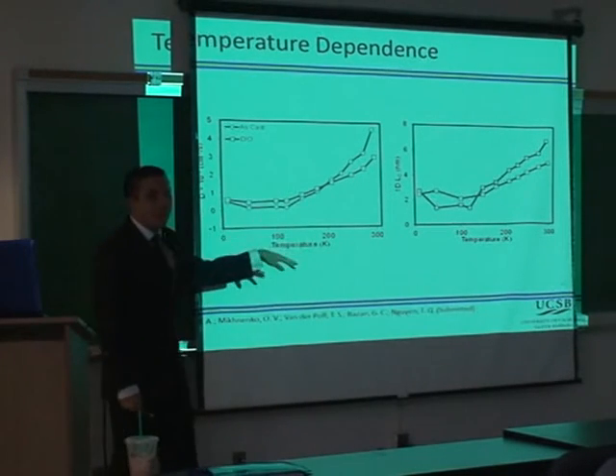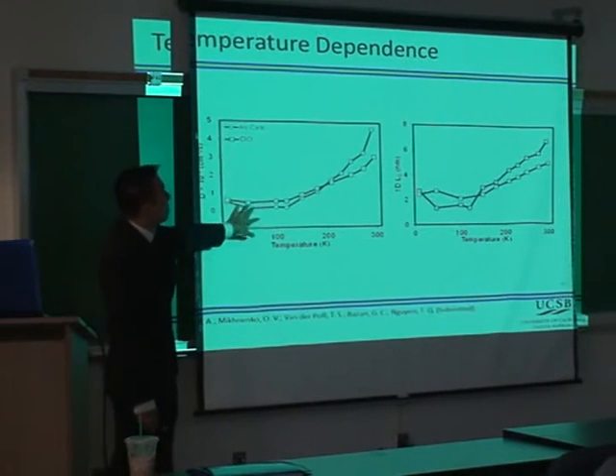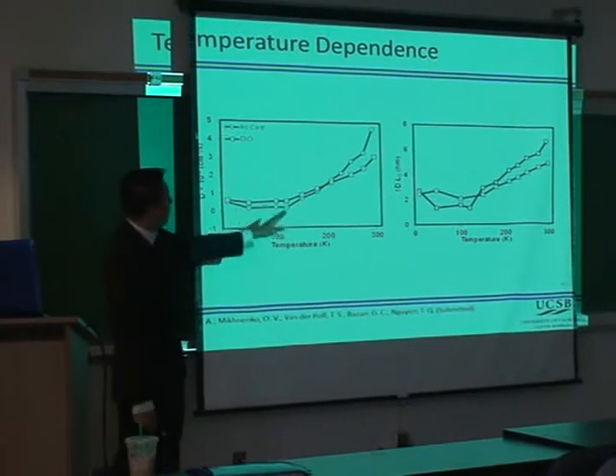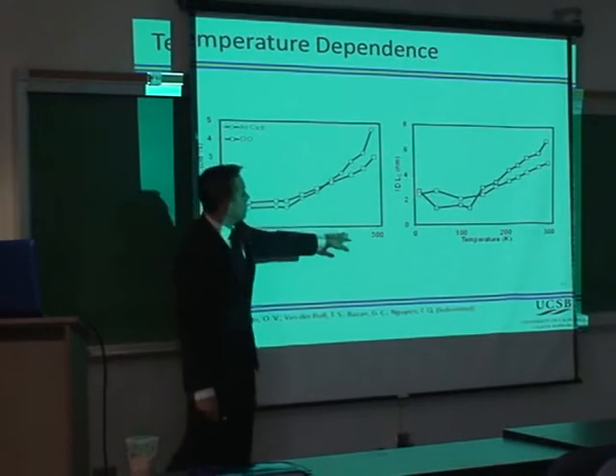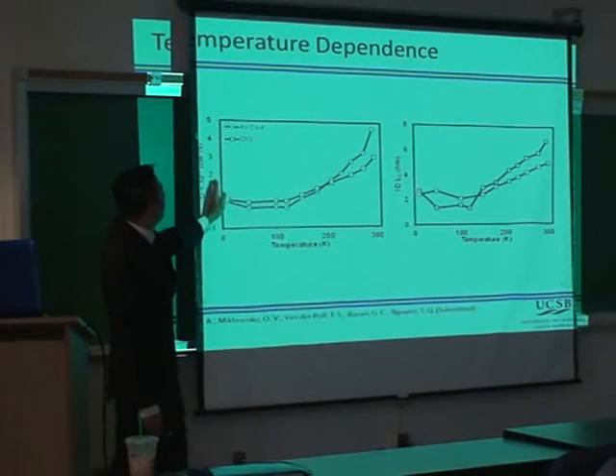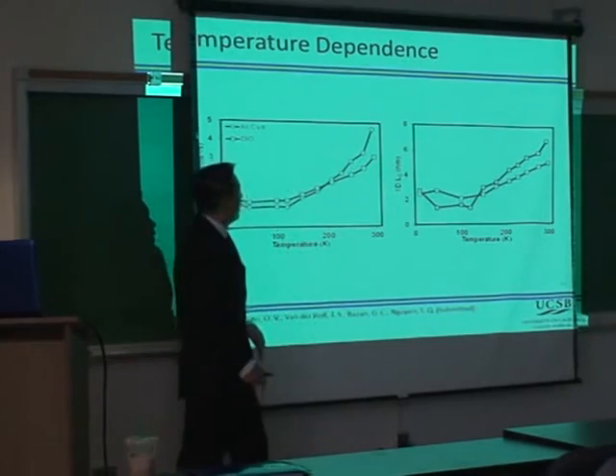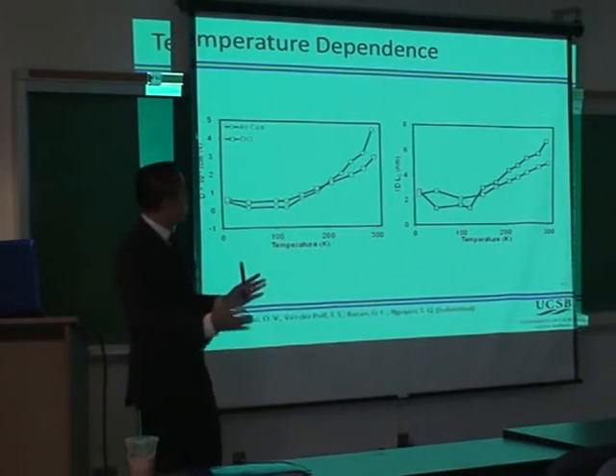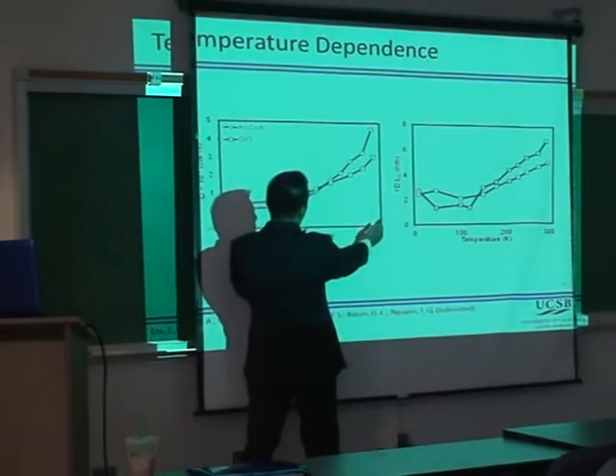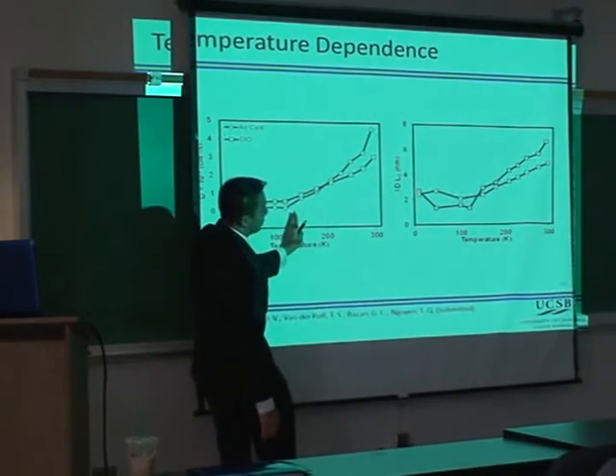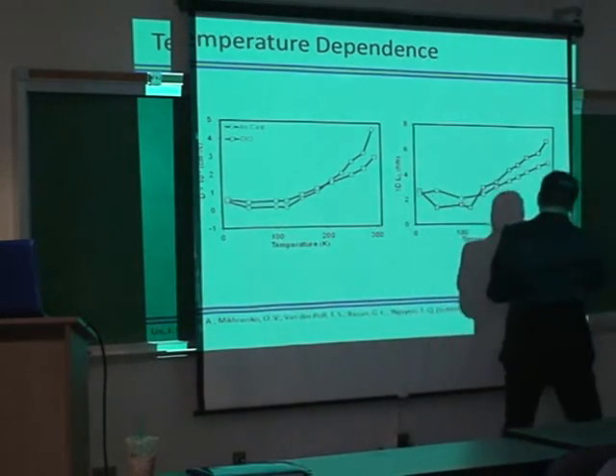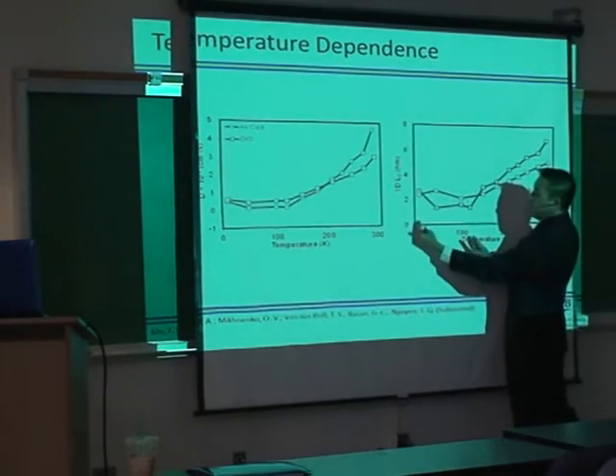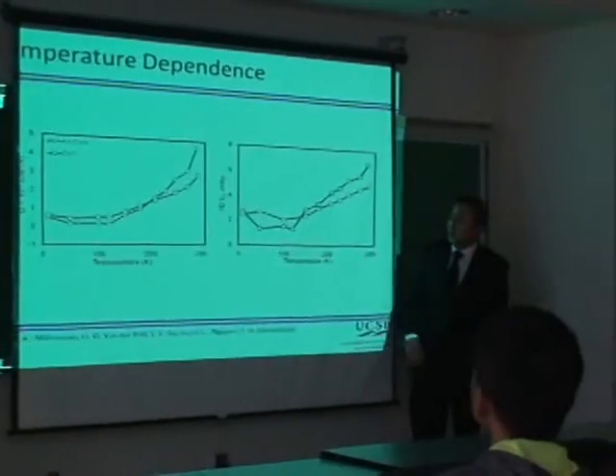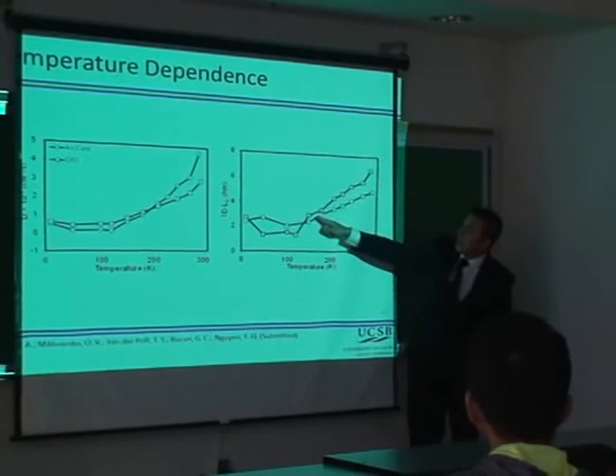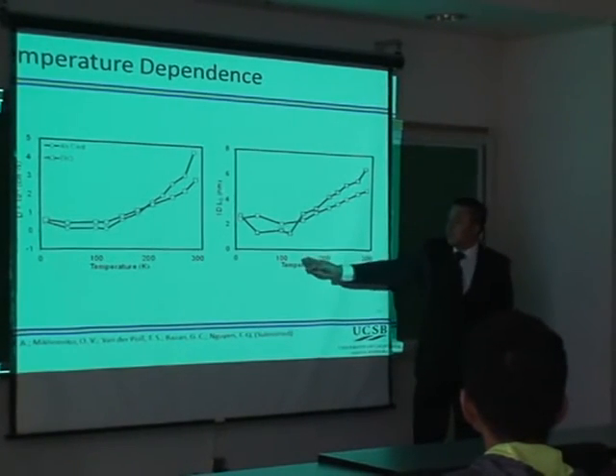We finally had all our results. I don't want to go through all the calculations, even though it took a long time, but I just wanted to summarize what our result was. What you see here is 2 different graphs where we have temperature on the x-axis and the diffusion coefficient on the y here, and the diffusion length here. What you can quickly notice is that there are actually 2 regimes. You have one regime from 300, around room temperature, to about 150 Kelvin, and another regime from 10 to about 150. And in this regime we have this increase in exciton diffusion length as you increase the temperature.